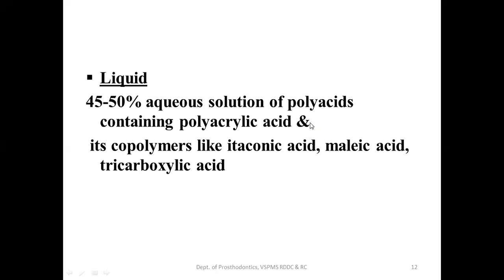tricarboxylic acid. Now these polyacids have many reactive carboxylic groups, and these groups are important because they chemically bond with the tooth enamel and the dentin collagen to give you chemical adhesion. Now these acids decrease the viscosity of the liquid, because if you remember in zinc polycarboxylate, we have seen that with polyacrylic acid the viscosity is increased, meaning it gels. So these decrease the viscosity. These 3 acids decrease the viscosity and also decrease the tendency to undergo thickening by gelation due to intermolecular